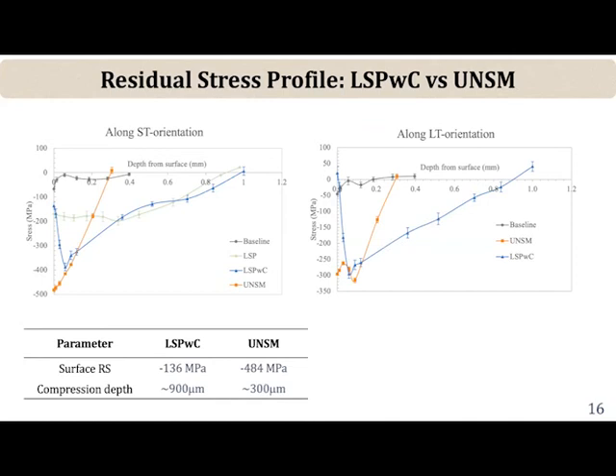So here you can see the difference. Now LSPWC here is compared with UNSM for one of those conditions. And you can see that here is LSP with tape, relatively low at the surface, but fairly high depth to almost 1 millimeter or so, along the ST orientation and along the orthogonal orientation.